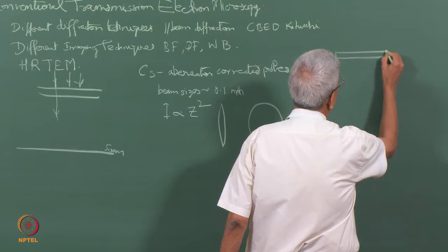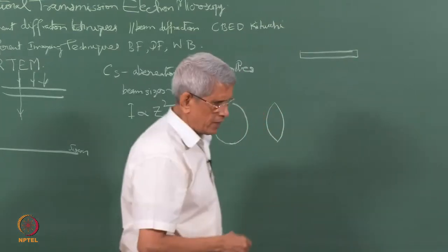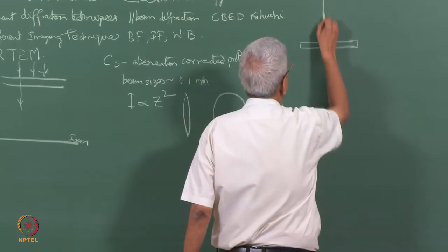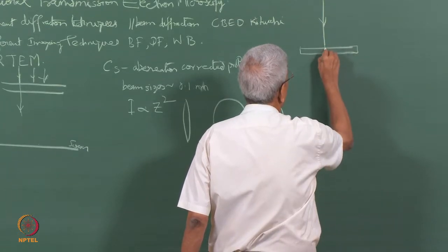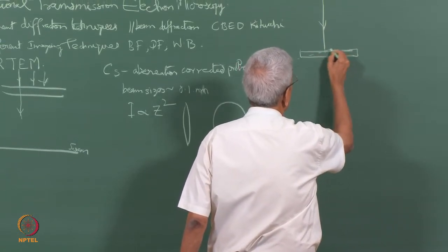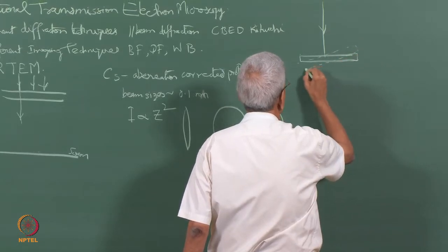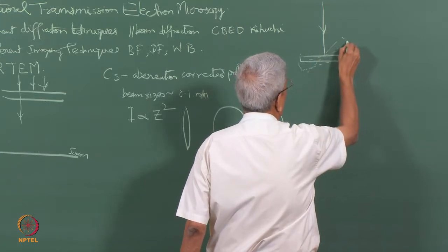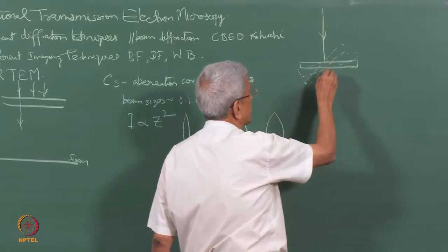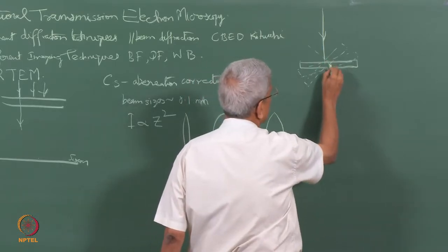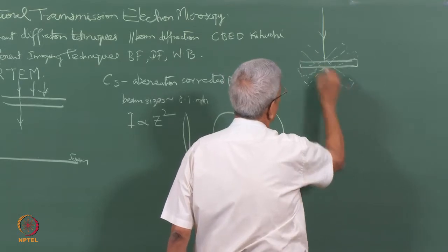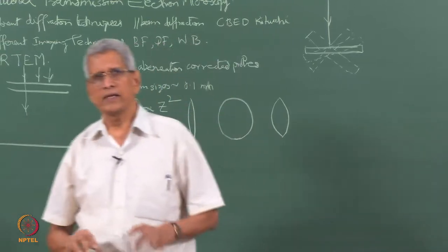we have a sample. The sample is put on a holder. Nowadays they call it a tomographic holder; special holders are available. Essentially, you keep a sample like this, make the beam pass through that sample, then tilt the sample gradually over different orientations, in both these directions, making sure that the beam falls exactly at that same area, and collect all the images which are formed